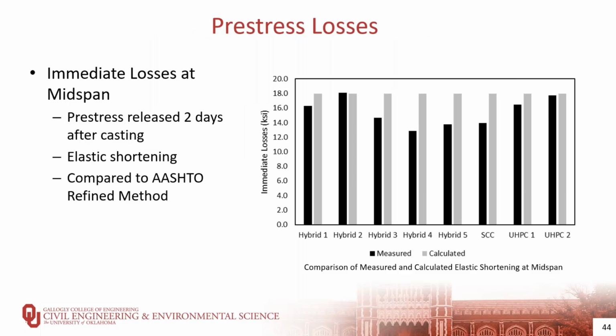In terms of immediate losses at midspan, the figure on the right shows the measured immediate elastic shortening losses compared to the calculated losses according to the AASHTO refined method. The elastic shortening was calculated from the measured strain obtained after pre-stress release, which was done 2 days after casting. In all the specimens, as can be seen from the figure here, the calculated elastic shortening was greater than the measured pre-stress losses, except for hybrid 2, where the losses were similar to the calculated value.